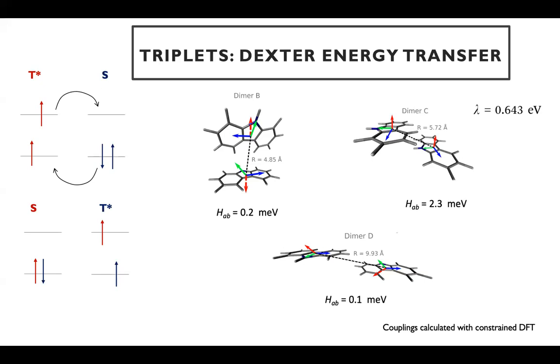And under these conditions, the main mechanism related to the transport will be Dexter energy transfer, where essentially what you have is something like this. You have your system with this electronic configuration. You may have the transition of one electron from this state to this one, and another electron from here, and you transform a triplet to a singlet, and you keep an excited triplet state. If you calculate this using constrained DFT, you can get the values of the couplings. They are also very small.